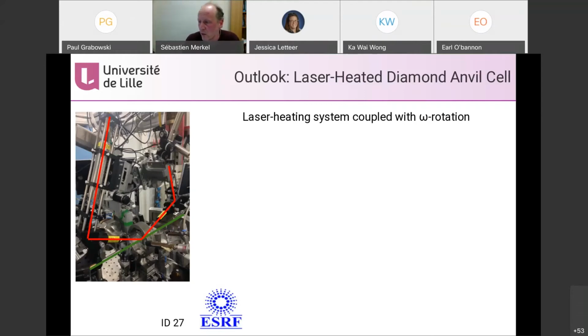So this is a drawing, this is a picture of the system. So the X-rays here are in green. The detector is to the back, the beam is coming from the front, and the sample diamond anvil cell will be sitting here. And this is a laser heating system that is shown in red. And it's being held by two huge arms, which you can't see on the picture, but below there is a rotation stage, and you can actually rotate that whole thing in front of the X-rays.